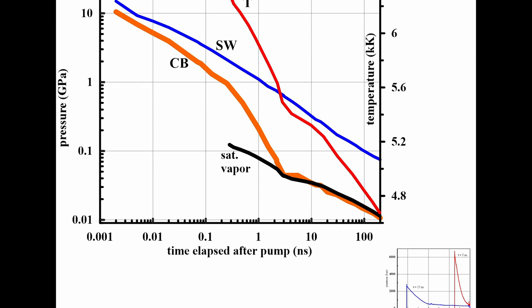But then it is supported by saturation pressure. This is the temperature of atmosphere in kilokelvin. So it is thousands of Kelvin. And this is saturation pressure for gold. And we see that after this drop, it is supported by the saturation pressure which is on the backside of the atmosphere. At the backside we have saturated pressure evaporation, and it supports the atmosphere, motion of atmosphere at this time interval.